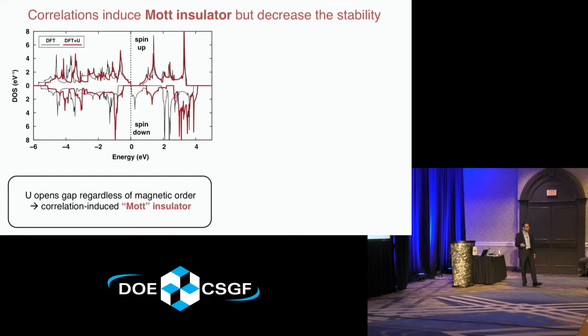And the interesting thing here is that, I'm not showing you, but we look at many other different magnetic configurations. So here all the spins are aligned, but we can look at ones that are anti-aligned in various configurations. And actually all of those are insulating. So what that tells us is that we are in that special kind of phase called a Mott insulator, in which it's not just some particular magnetism that's leading to the insulating behavior, but it's actually the electronic correlations themselves.